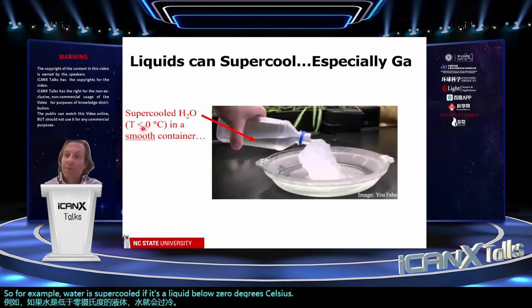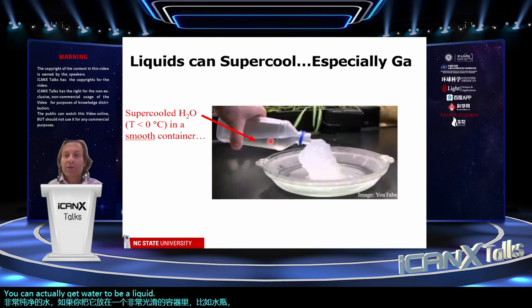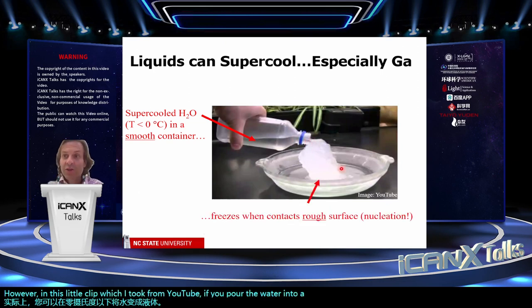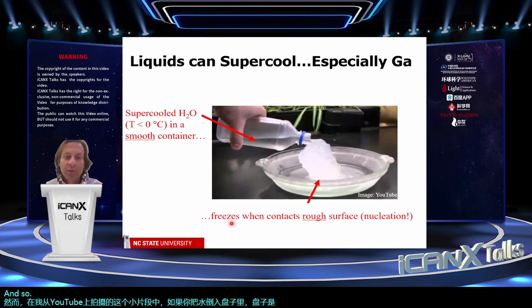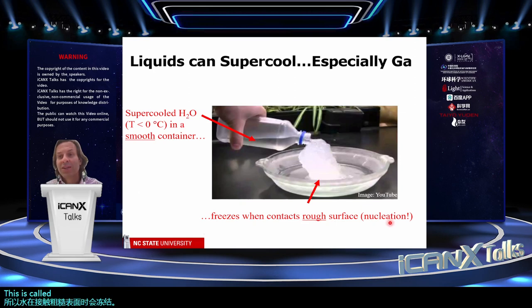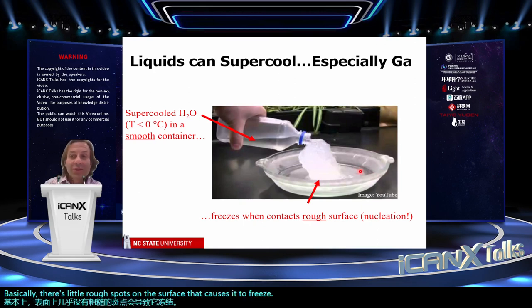How does this happen? Well, if it's very pure water, and if you have it in a very smooth container, like a water bottle, you can actually get water to be a liquid below 0 degrees Celsius. However, in this little clip, which I took from YouTube, if you pour the water into a dish, the dish is rough. And so the water will freeze when it contacts a rough surface. This is called heterogeneous nucleation. Basically, there's little rough spots on the surface that cause it to freeze. So it wants to freeze, but it can't until it touches a rough surface.